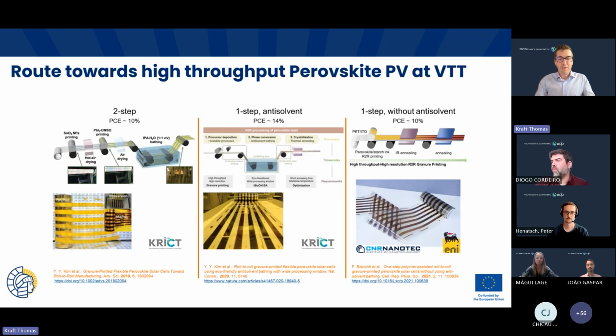To give you an idea of what I mean by the printed perovskite, many of you might not be so familiar with this, but these are examples that we've done at VTT on our roll-to-roll lines. I would say about 7 or 8 years ago, we started to work on this. And it started off with this 2-step approach. What I mean by that is you print a precursor, then in another step, you print the next component of the perovskite, and then you go through a crystallization bath. And this separates the processes to have very controlled crystallization of your perovskite active layer.